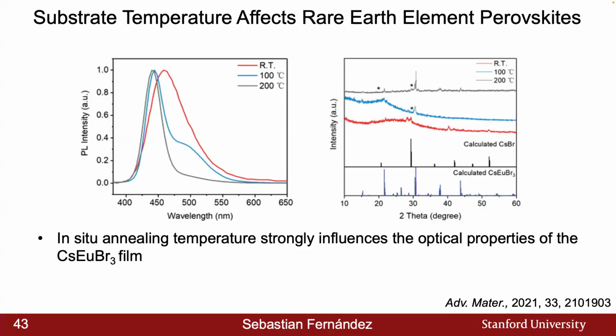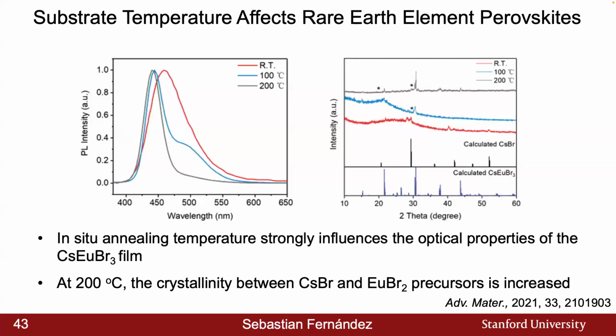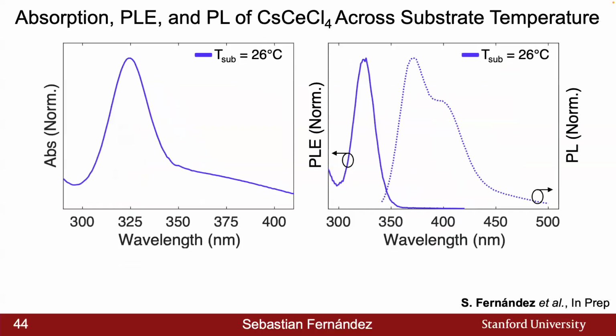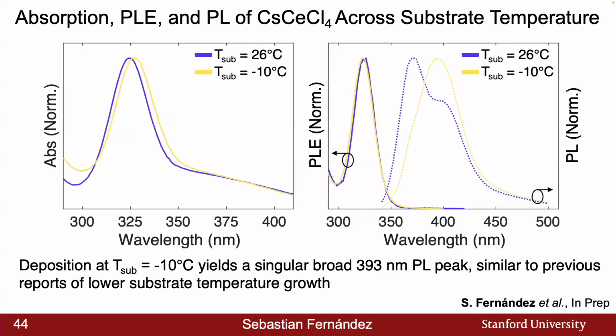And as well, from the XRD, you can see a greater increase of the crystallinity between the cesium bromide and cesium europium bromide as moving to higher in situ annealing temperatures. So we have a similar capability within our lab in which we first, again, we've already shown the pure chloride-based system at room temperature, but then moving to a lower temperature of minus 10 degrees Celsius, we start to see very similar, this singular broad peak, which again is similar to the previous reports, implying that maybe there was an underreaction between cesium chloride and cerium chloride.